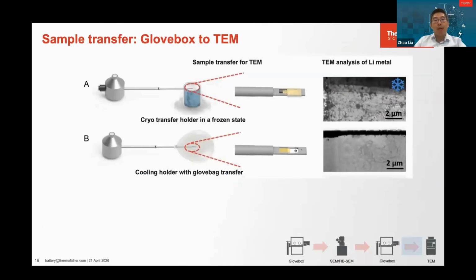Then the next step is the sample transfer from the glove box to the TEM. Even if you have a good, high quality lamella, it can still go wrong. This showcases an example where you use either a cryo transfer holder or a cooling holder for the transfer process. With the cryo transfer holder, your sample sits in the liquid nitrogen tank and you transfer it through the cryo transfer holder to the TEM. Because moisture can attack the cold surface, it forms ice crystals, as you can see in row A, where a lot of ice crystals formed on the samples. If you use a cooling holder with a glove bag for the transfer, there is a short exposure time between removing the glove bag and inserting into the TEM, and even a few tenths of a second will give you contamination on the surface.